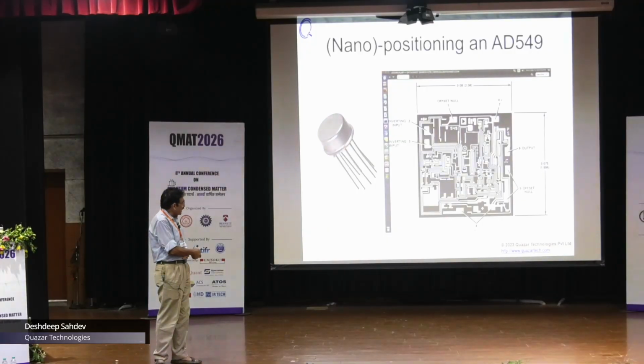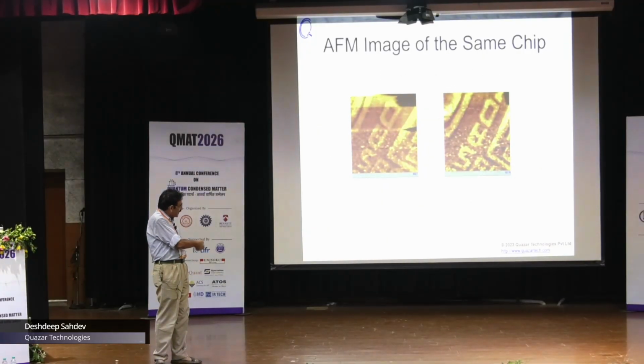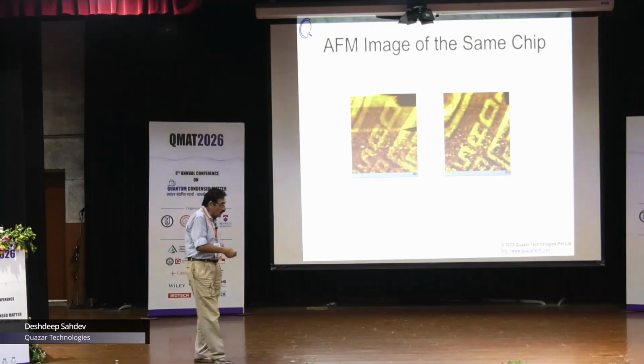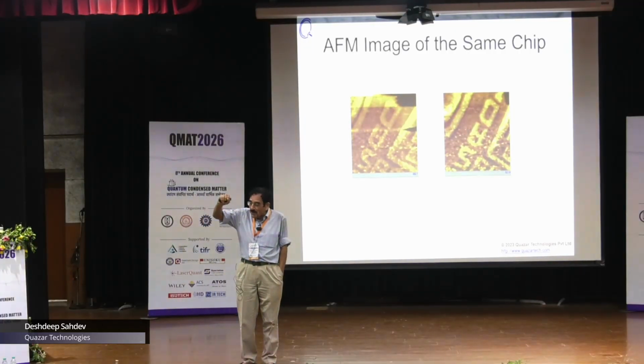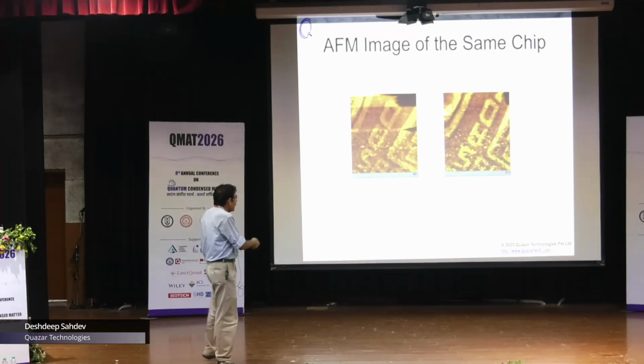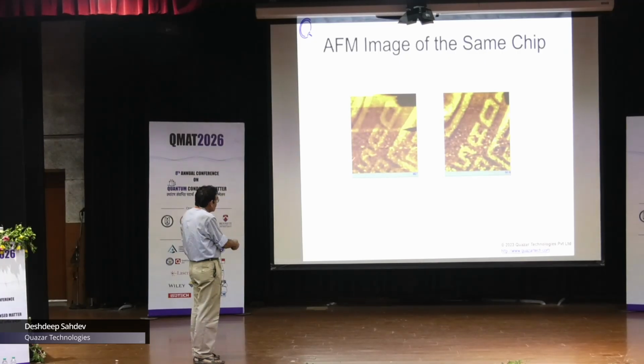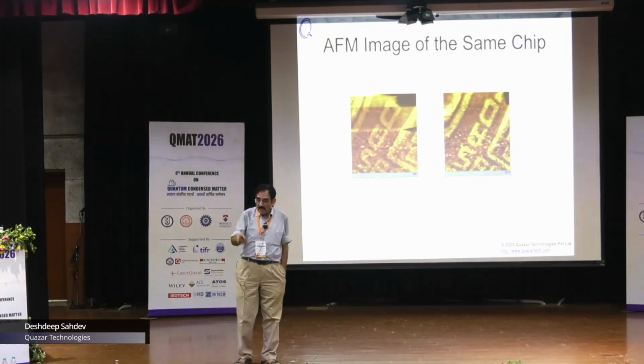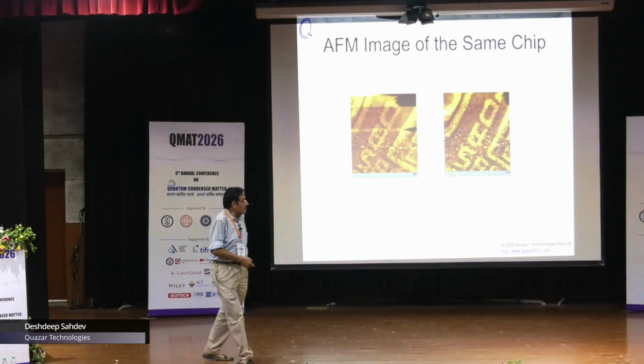Opened out that chip and then scanned it with this, and you use just that shift in frequency in order to image this. And you could see this is the first image that we got with ADI in 1985 using the AFM and the whole feedback loop. And we've taken that further.